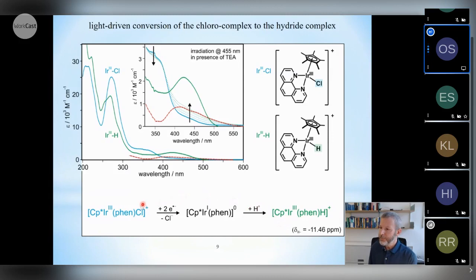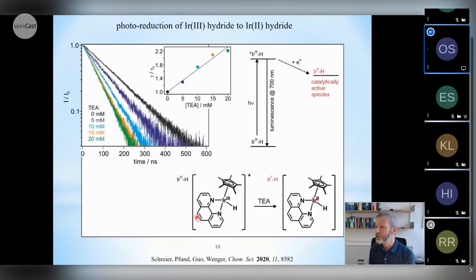And so likely what happens here is that the iridium-3 chloro complex undergoes reductive dehalogenation to this well-known and actually isolable intermediate. You can protonate this and you will get the iridium-3 hydride. In principle, outside photochemical scenarios, in electrochemical settings, this chemistry is well known and well established.